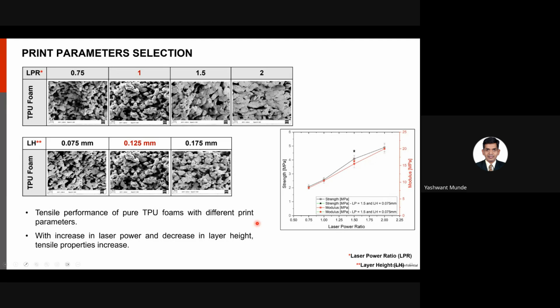So first we looked at the tensile performance. As we increased the laser power, we saw that the strength and modulus increased. And with increase in laser power and decrease in layer height as well, we saw that the tensile properties increased. For example, the star here is a laser power ratio of 1.5, but with reduced layer height. So we see that there is a slight increase in properties when we reduce the layer height as well. So we chose 1.5 and 0.075 as our parameters to print the consequent structures. We could go to 2, but we would be reaching the limit of the machine, so we did not want to mess with that. And 1.5 did show an increased wall thickness.